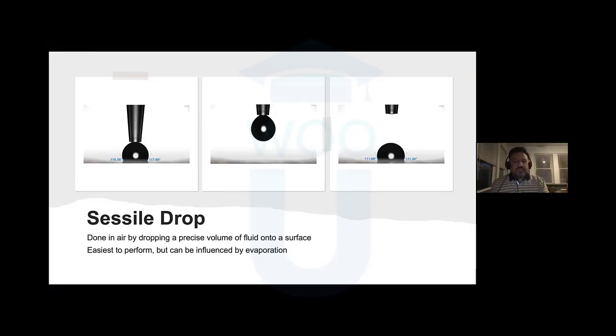The sessile drop is simply dripping or dropping a very precise volume of liquid onto a surface, and then watching how that liquid spreads out over the surface and measuring the angle between the surface and the edge of that bubble of fluid. And so this is how it works. And it's easy to perform this given the proper instrumentation to drop a very precise amount of fluid onto the surface. The only negative is that evaporation can occur rather quickly, which does sometimes affect measurability, accuracy of surface wettability using the sessile drop method.